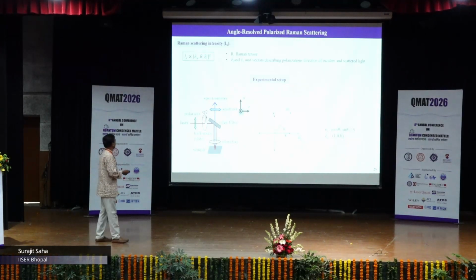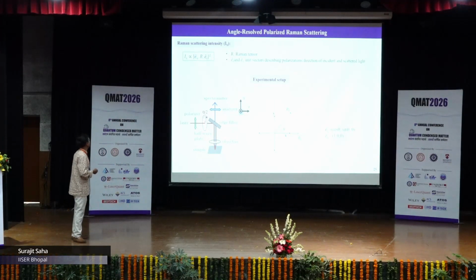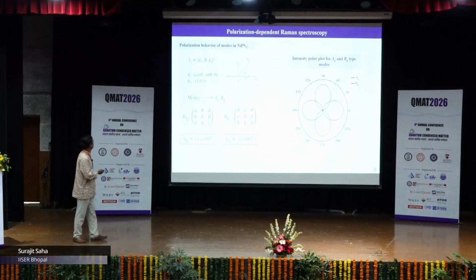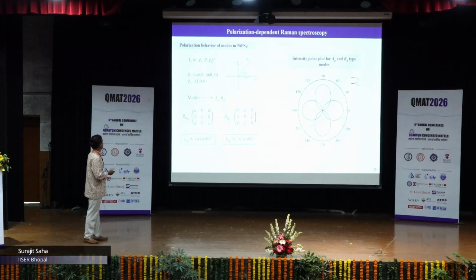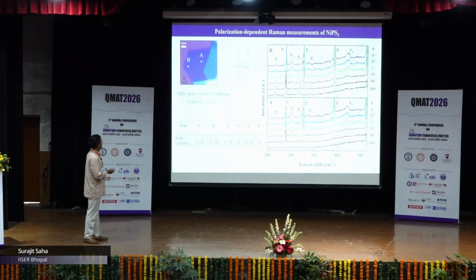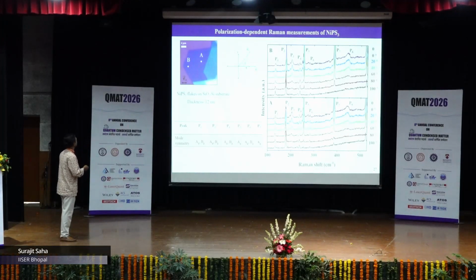So we looked at angle resolved polarized Raman, and based on that, these are some calculations that we had to do. I'll show you the results here. This is the flake, which is roughly about 12 nanometers thick, and these are the various spots where we looked.